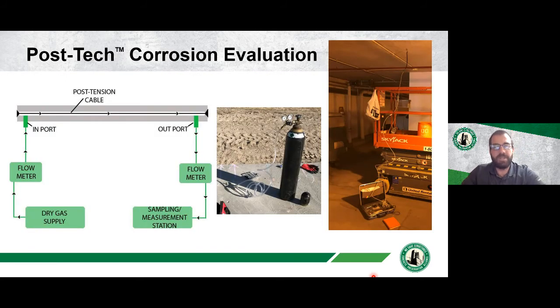So one of the tests that we do is post-tension corrosion evaluation. So what we do is we make a port on either side of the tendon. We push dry air into the port, and then we measure that dry air coming out and measure the RH and temperature of that air. And if that dry air is picking up moisture and we measure that out here, then we know that the tendon is potentially wet or has a risk for corrosion.